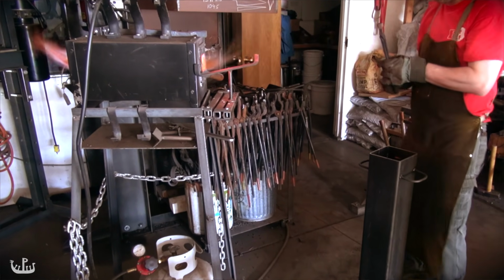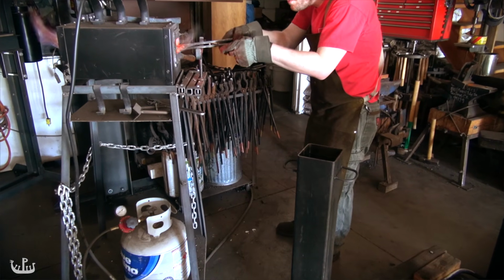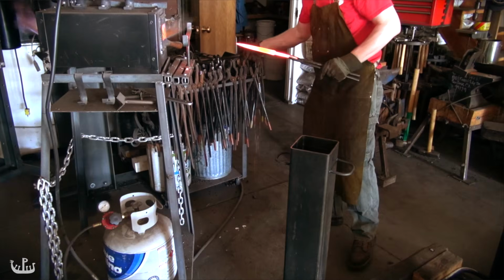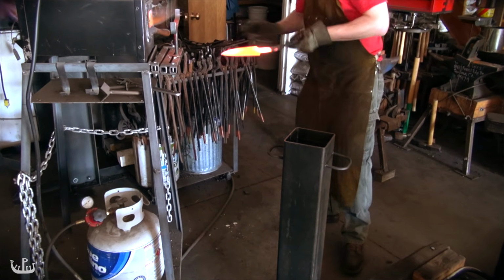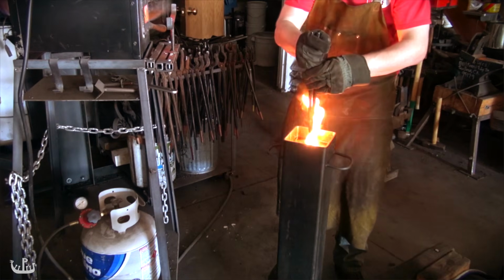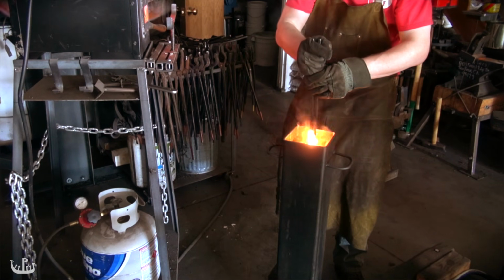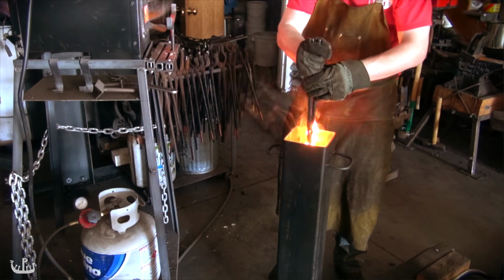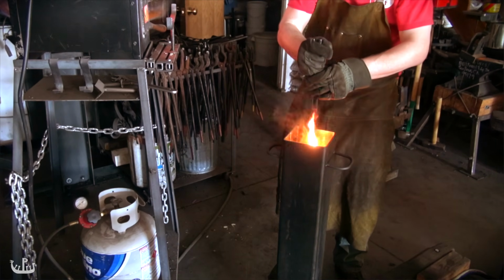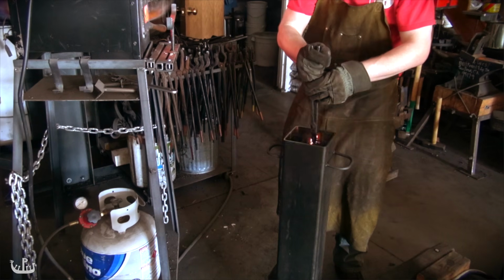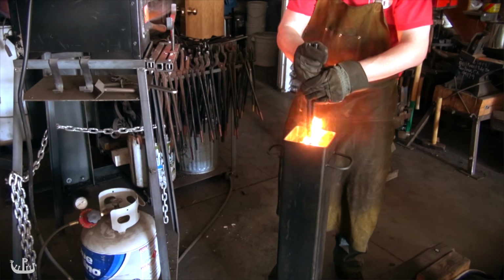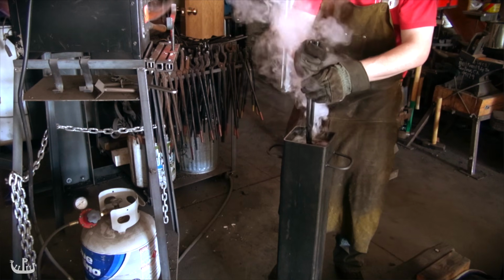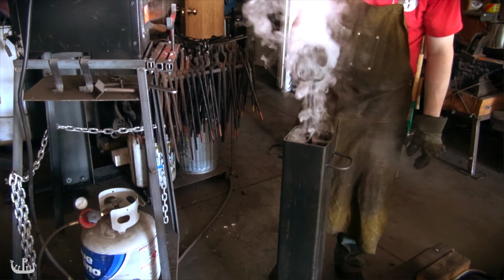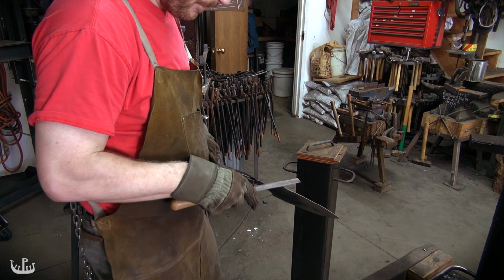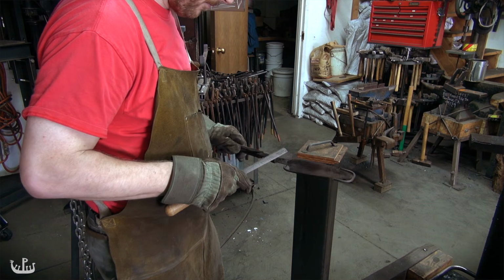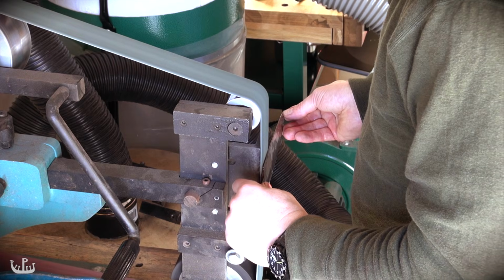To harden the knife, the blade is heated up to its critical temperature, in which the carbon is dissolved in the iron matrix forming austenite. Quickly cooling it down transforms the austenite into hard martensite. I use a file to test if the blade successfully hardened. If the blade is hard, the file will just skid over it. After quenching, I temper the blade at 500 Fahrenheit for an hour.